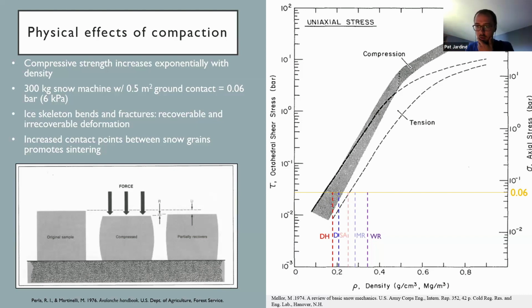I didn't include the Mayo sites on this graph, because they're very homogeneous and they all averaged about 0.18, except the dendritic snow, which was 0.14. So that puts all the different snow types in the smushing range, which explains why there was depth reduction throughout the snowpack. The bottom diagram shows how snow reacts and recovers from pressure. The ice skeleton partially breaks and partially bends, with the bending part recovering once the pressure is removed. This explains why repeated compactions didn't always translate into equally large differences in snow conditions. The first compaction will crush the weakest bonds, and subsequent compactions will have progressively less effect.